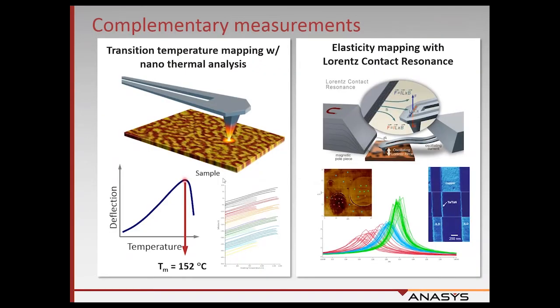Just very briefly, a couple of final complementary measurement techniques. I mentioned this one earlier, this nanothermal analysis, where we can use a heated AFM tip to locally ramp the temperature of the sample right underneath the probe apex, and we can measure softening temperatures like glass transition temperatures and melting temperatures. And then we have a wideband nanomechanical spectroscopy technique called Lorentz contact resonance that lets us map the sample stiffness. We can take mechanical spectra and also get mechanical stiffness and damping images.